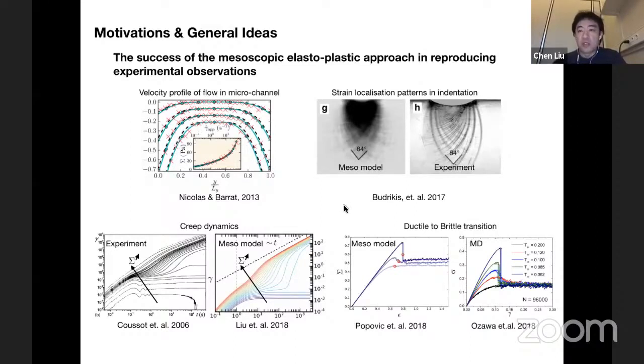The second example is an indentation experiment when you press with a small rounded surface to an amorphous material. And this picture shows the patterns of strain localizations in experiment, which can be actually somehow well captured by elastoplastic model also.